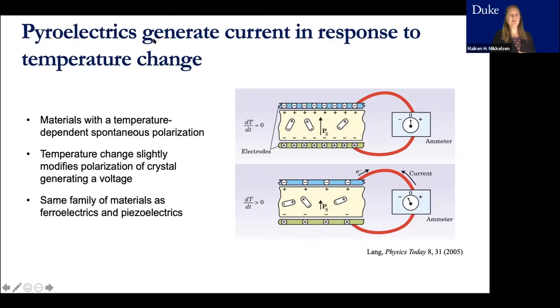These are not as well known. The way they work is that they have a temperature-dependent spontaneous polarization in the crystal. So this is where you have no temperature change, but when you have a small temperature change, the polarization in the crystal slightly changes, which causes a current to flow. This is the same family of materials as ferroelectrics and piezoelectrics, which are much better known, where you can change the spontaneous polarization with the electric field or by strain or pressure. But for the pyroelectrics, we are changing the spontaneous polarization by applying heat.